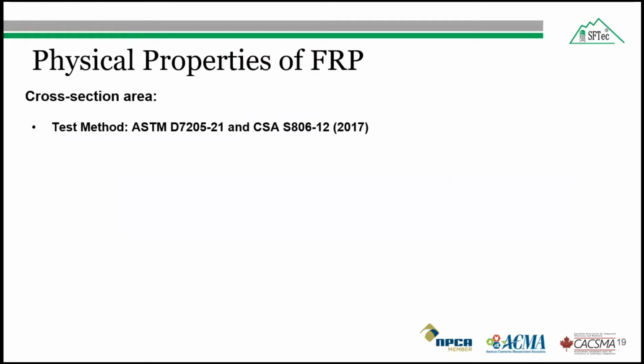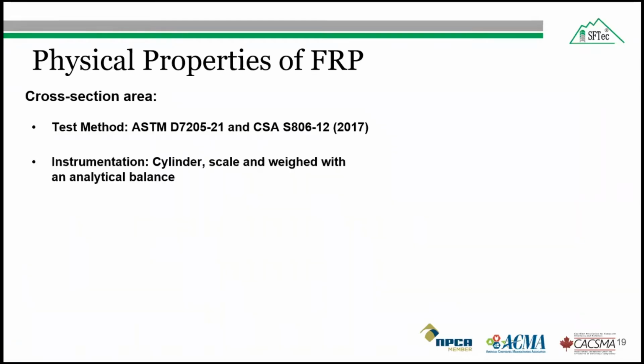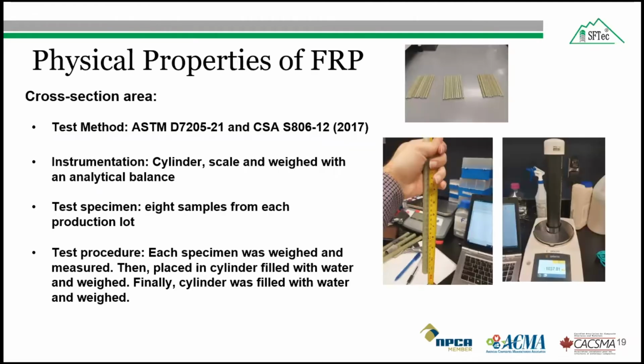The next physical property is the cross-sectional area, and the specimen generally were tested in accordance to the ASTM D7205 2021 and CSA S806-12 for the cross-sectional area of the fiber reinforced polymer bar. So the instrument used in this test were cylinder and measuring scale, and the specimen were weighed with an analytical balance to 1 milligram precision. So again, 8 samples from each production lot were tested, and each fiber reinforced polymer specimen were weighed with an analytical balance to 1 milligram precision, and measured carefully with a measuring scale, and then the specimen were placed in a cylinder filled with water and weighed, and finally the cylinder was filled with water and weighed separately.